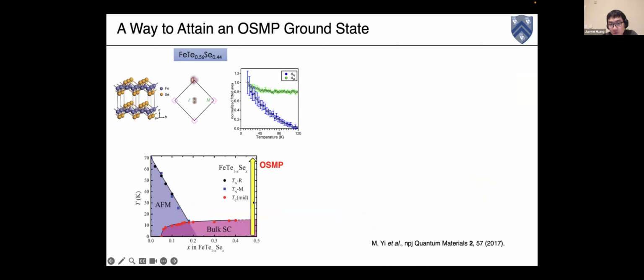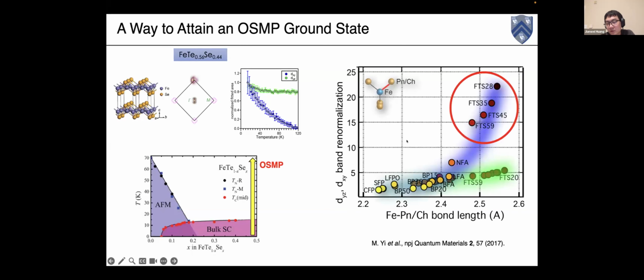But one thing is that for the temperature-induced OSMP phase, it's very hard for us to study the electronic structural evolutions across the orbital selective Mott transition, because at high temperature, the spectral weight is going to be very incoherent. The data we get is going to be very fuzzy. We will not be able to really see the clear electronic structural transition. So we want to really look at the orbital selective Mott transition that happens at a very low temperature, even the ground state. If you look at the FeTeSe family, we find that if it goes toward the iron tellurium end, the effective mass or the renormalization factor of the dxy orbital increases dramatically, even exhibiting a divergent behavior, which strongly indicates that the OSMP in iron tellurium may happen at a very low temperature, even the ground state.